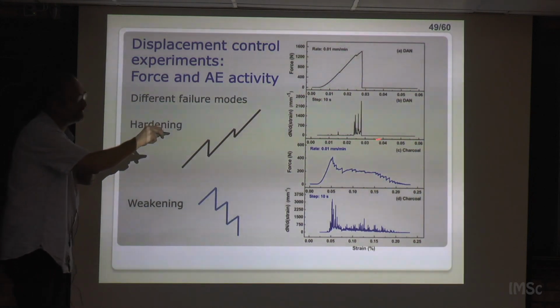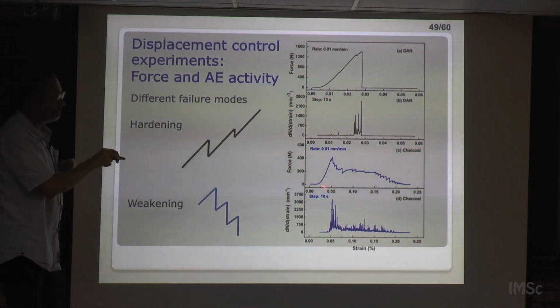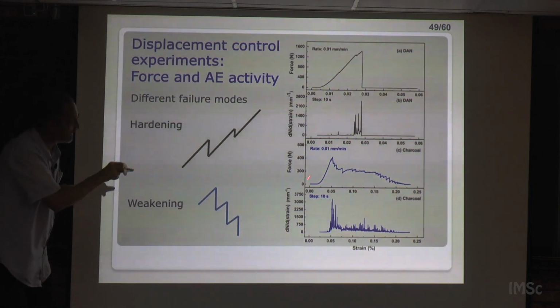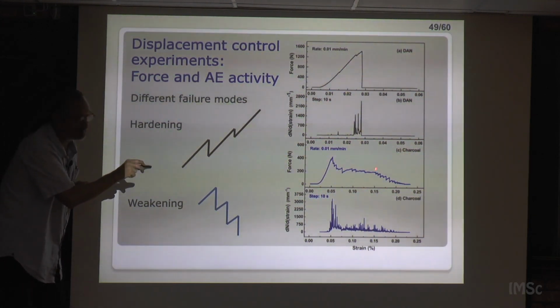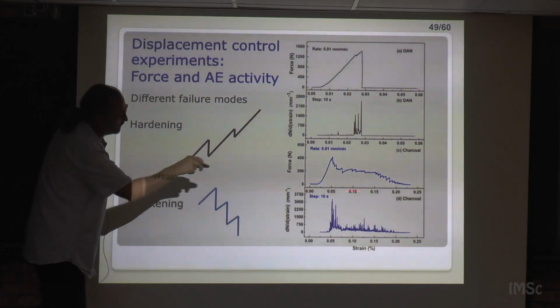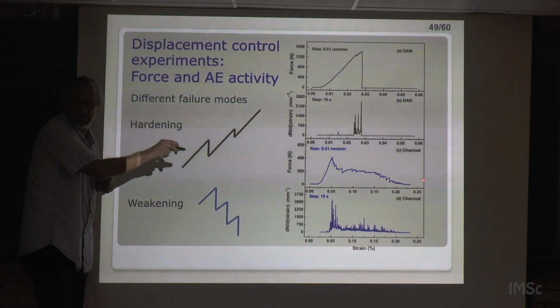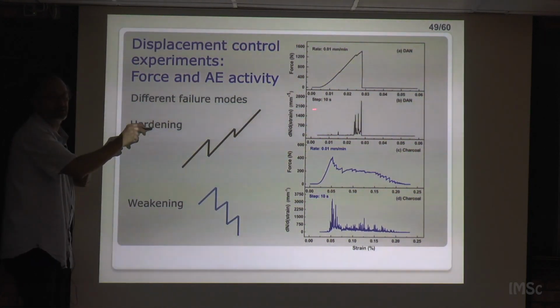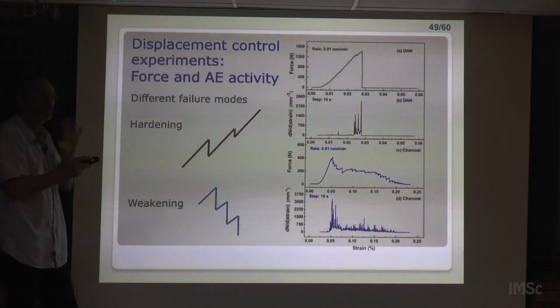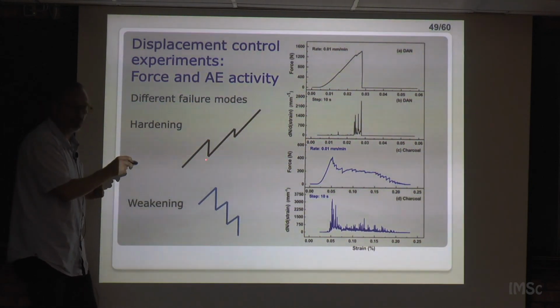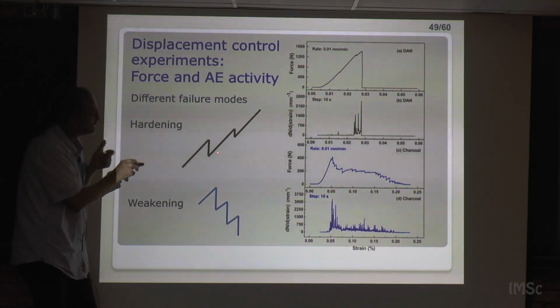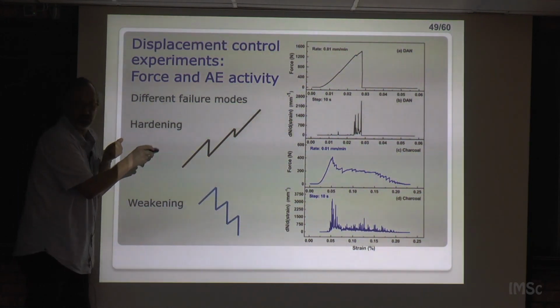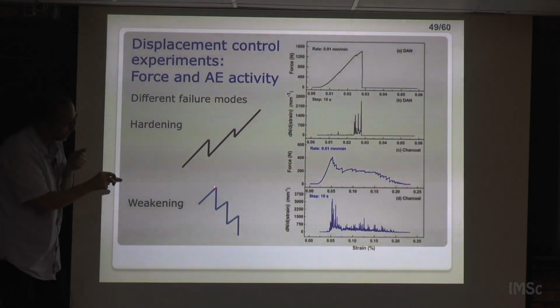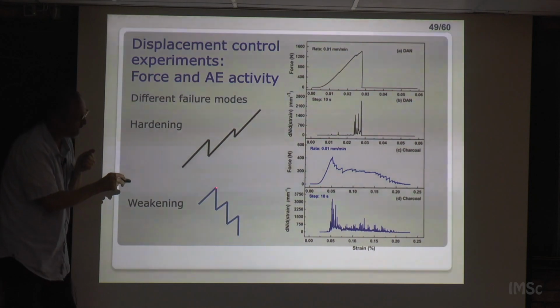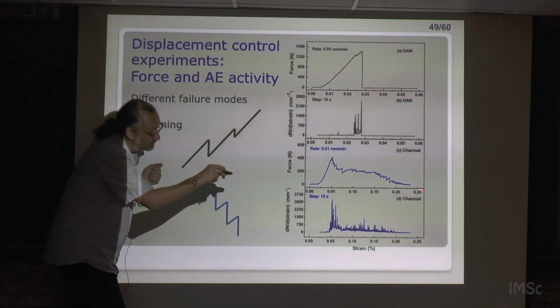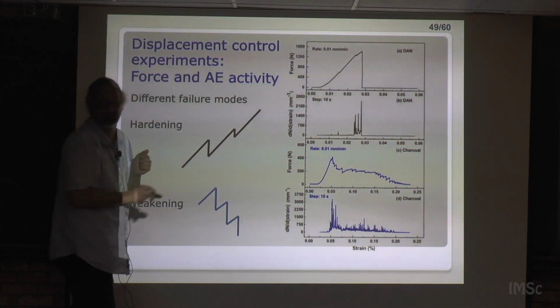And this is the acoustic emission activity, number of events per time. But in other samples, you have this. It goes elastically, and then it starts to decrease like that, for a much longer time than here, or much longer strain than here. It supports much more strain in this case. These are what we call hardening materials, hardening samples. I call it hardening. I don't know if this is the common name, because after failure, on most occasions, the sample is able to go to larger forces. Whereas I call this one weakening, because after failure, the sample never recovers that force. So you see this slope here, whereas here, that's it, essentially.